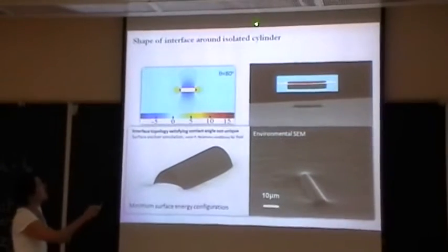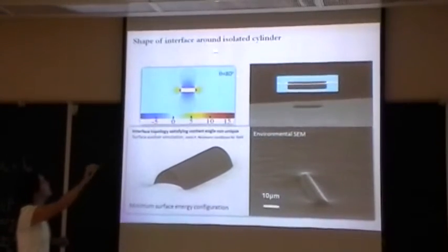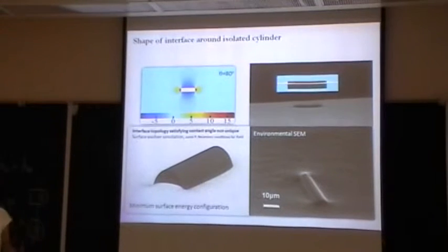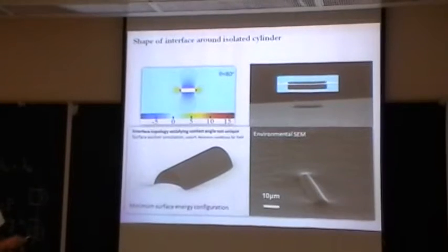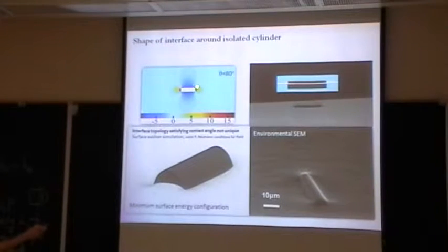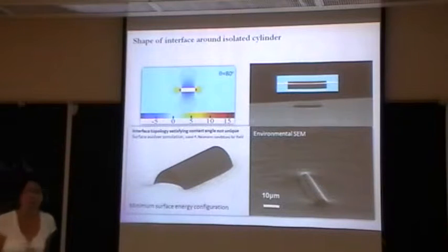And so this is the wetting configuration. And far away from the particle, it becomes a quadrupole that one could describe in polar coordinates or cylindrical coordinates. But closer in, there are important distortions that are happening. We see the rise at the end is about 3 times higher than the fall of the sides. Okay, so somehow the rise is being concentrated at the end here. But then we want to say, well, if this is a numerical prediction, how does it compare to experiment? And it does okay. This is a particle trapped in jello.